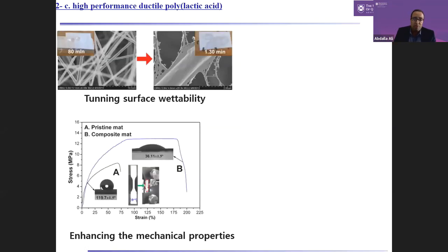Not only that, we use this technique with PLA, polylactic acid, an FDA-approved material widely used in stent applications, drug delivery, or implantations. But the main limitations of PLA are its hydrophobic properties and low mechanical properties, because it's a brittle material. To address this, we use polyvinyl alcohol. It's an FDA-approved material as well. We prepare a solution, immerse the electrospun scaffold in it, and heat it up